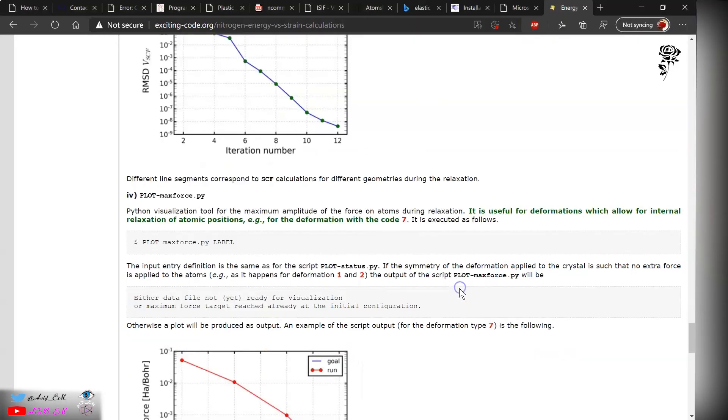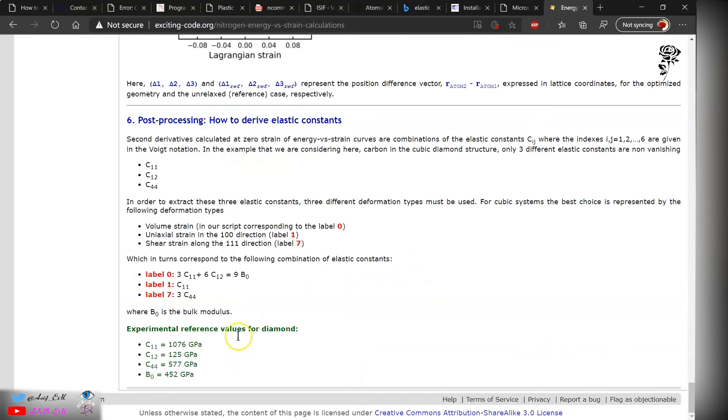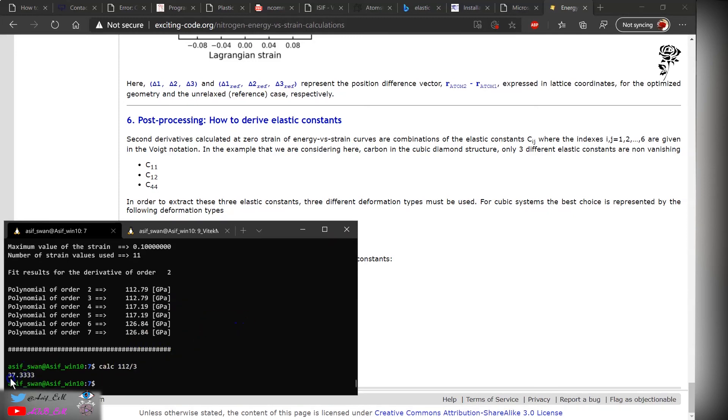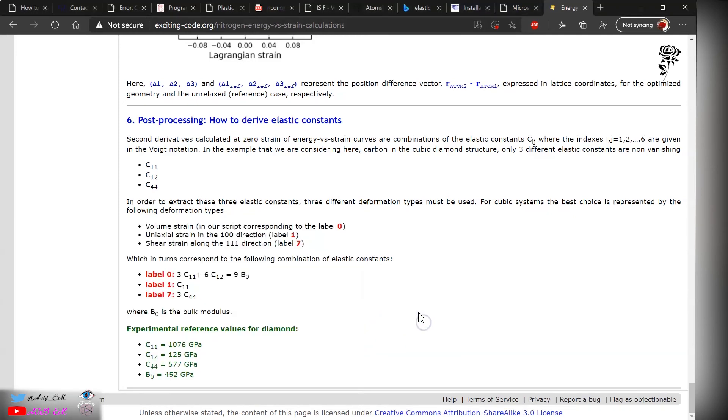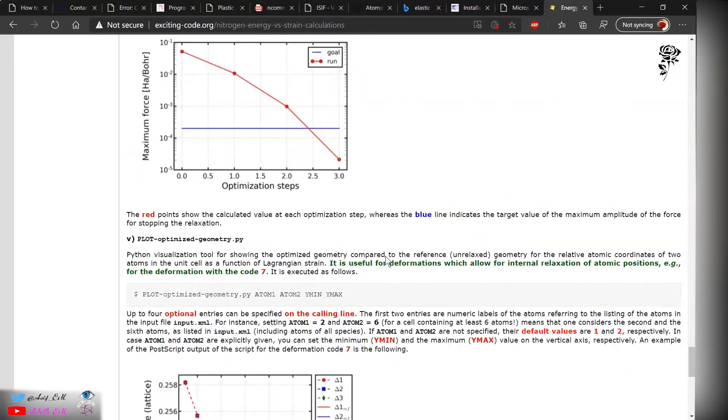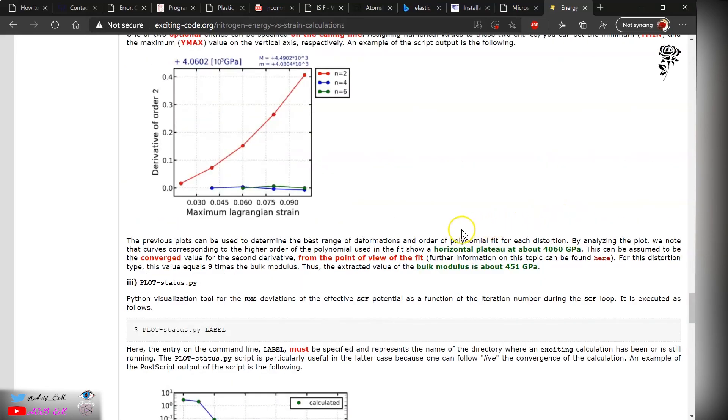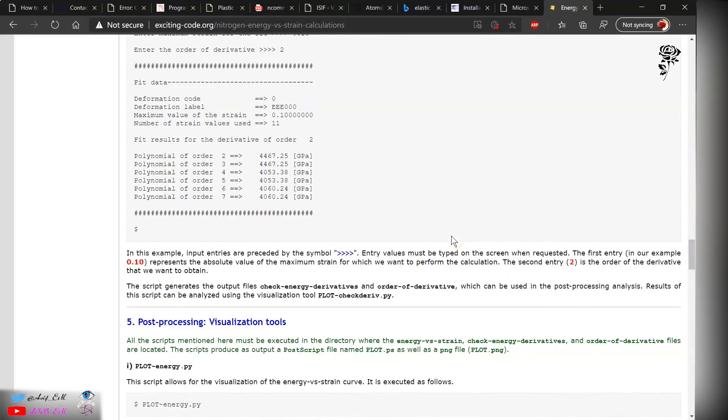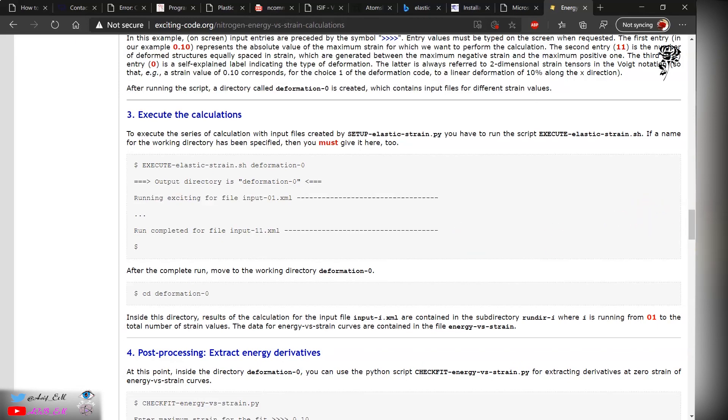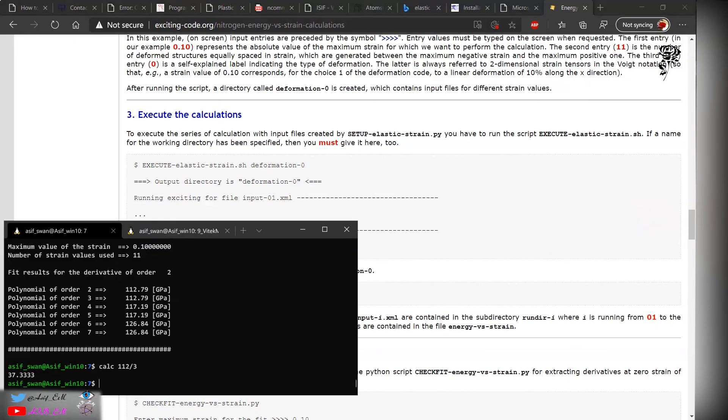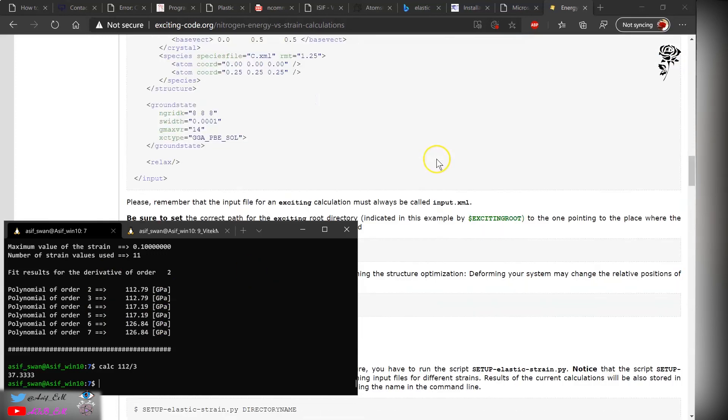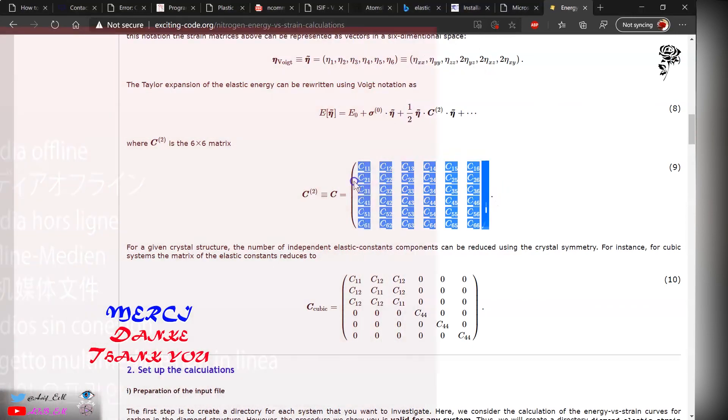To deduce the shear value, you can go down the page. Over here, this value is given by three C44. When you want to deduce this value, you will get the C44 value over here. Similarly for bulk modulus, we got this value. You divide by nine, you will get the bulk modulus. From this analysis from volumetric, you can obtain the lattice parameter. But I have to warn you, for high entropy alloys, these constants are not perfect cubic, they are distorted. So we have to calculate the whole elastic constant matrix. That's it for this tutorial, thank you.